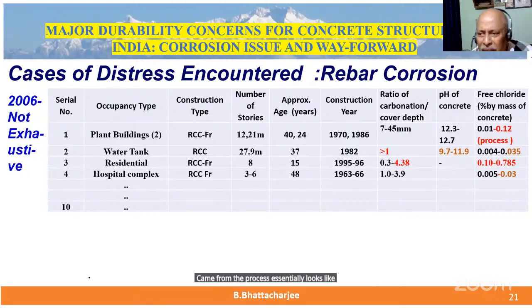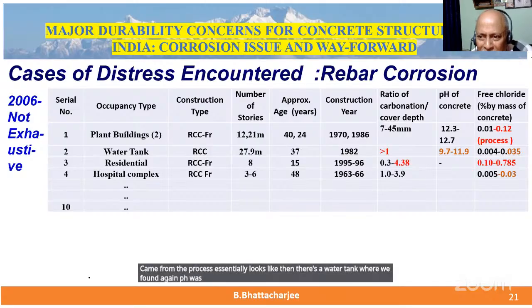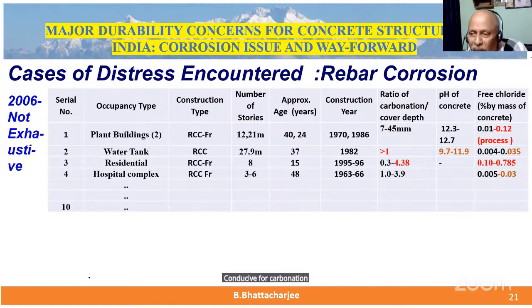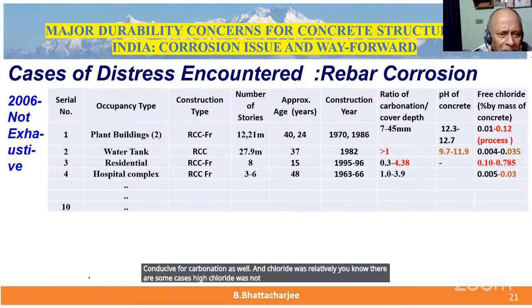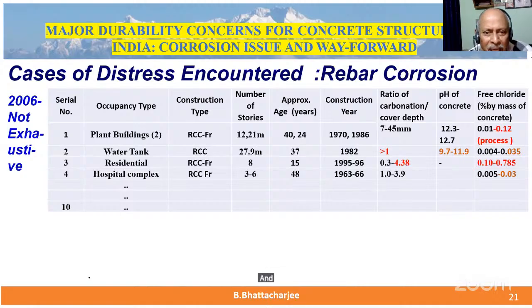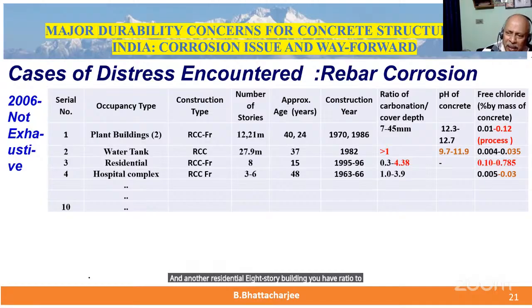Then there's a water tank where we found again pH was relatively lower, and carbonation to cover depth was higher. The point that I'm making is, a water tank means the moisture condition is conducive for carbonation as well. And chloride was relatively, in some cases high chloride was not much really. Hospital complex, 48 years, I think chloride was pretty low, but carbonation to cover depth was high. And another residential 8-story building, the ratio to carbonation depth was also fairly high, and chloride was also high.